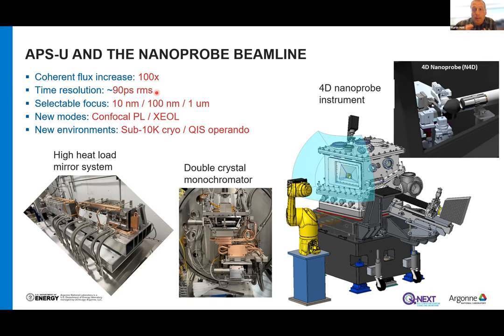I'm coming at it from the back end of, hey, how fast can I scan, and when do I need to stop before I take images? The sparse sample ptychography is key to that, because you can tune a way lower dose gradient than you would think in order to get a high-fidelity image with this deterministic smart scanning of defocused beams that aren't even overlapping with each other. Do you see what I mean? So I feel that the analytical techniques and the scanning capabilities are going to meet in the middle a bit to help, but it's obviously a huge concern.